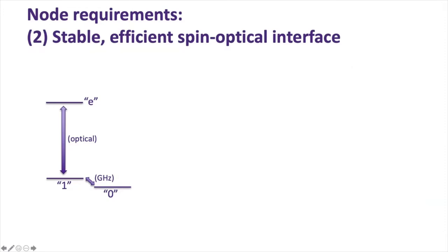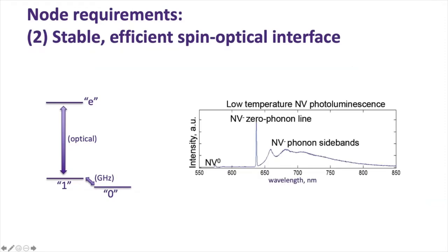Okay. And then the next thing that we need, other than these very stable long-lived memory states, is this optical transition. What we typically do in the lab is we excite the defect and we look at the photoluminescence that's emitted from the defect. So here you can see the intensity of the light that's emitted as a function of the wavelength of the light. And 637 nanometers is the transition of interest for the nitrogen vacancy center for these types of applications. It's a very, very sharp line that's called the zero phonon line. I'm going to talk a little bit more about this, but this zero phonon line has been used for creating small scale quantum networks. And this wavelength is in the red.